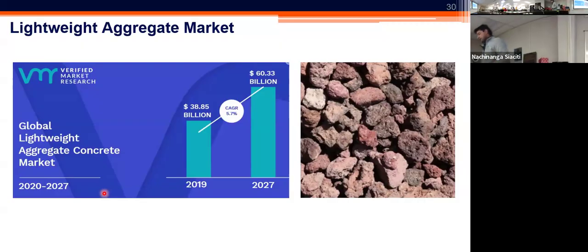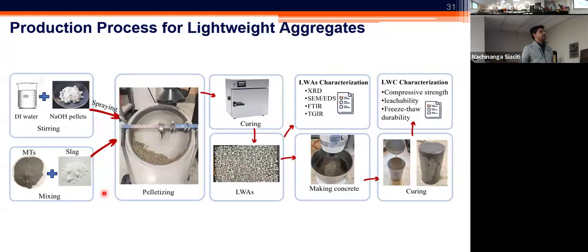So we had this motivation, and as the first research group, we started to look into the process of the production of the aggregates from the mine tailings. So with a small tweak in our process where we are still using the alkali activator by simply spraying the alkali activator on the pelletizer, we were able to produce the aggregates in the form of the pellets that then would undergo the curing process and then incorporation into the concrete.